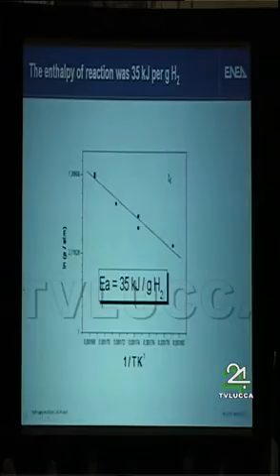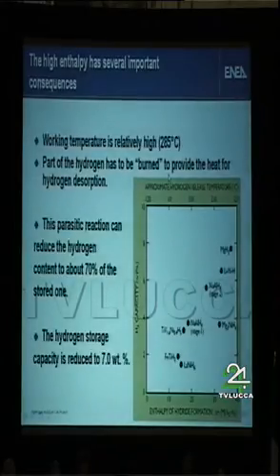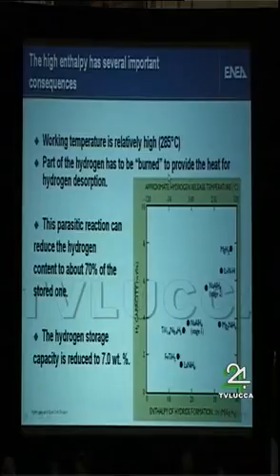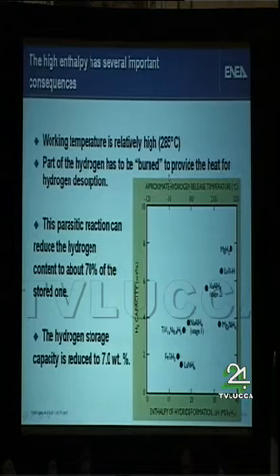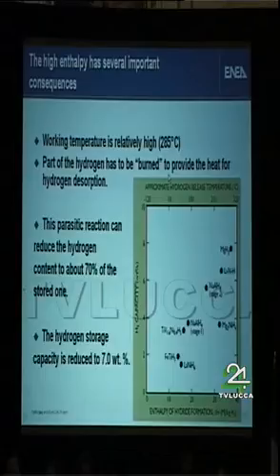The high value of the enthalpy has several consequences. The working temperature is relatively high. Part of the hydrogen has to be burned to allow other hydrogen to desorb, and the parasitic reaction can reduce the hydrogen content to about 70%, so only about 7% of hydrogen can be stored in lithium nitride. It means that it could meet short-term DOE goals, but not long-term goals.